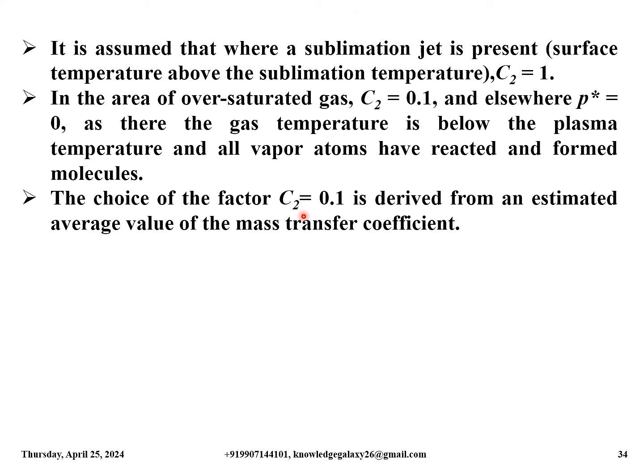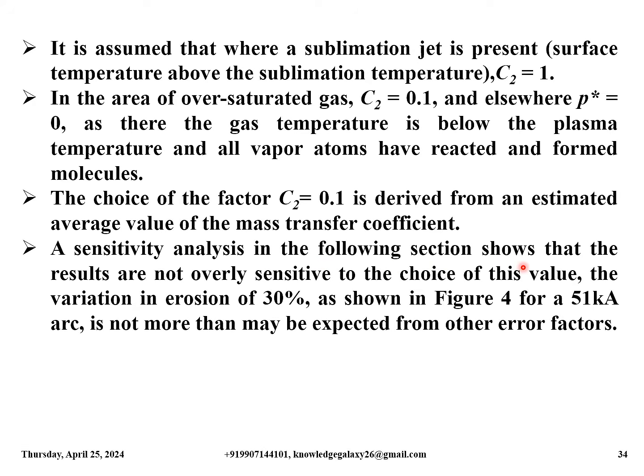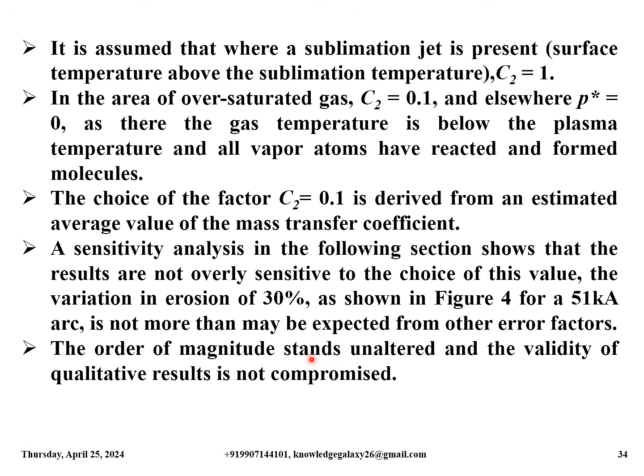The choice of the factor C2 equal to 0.1 is derived from an estimated average value of the mass transfer coefficients. A sensitivity analysis in the following section shows that the results are not overly sensitive to the choice of this value. The variation in erosion is 30%, as shown in figure 4 in the coming slides for a 51 kA arc, which is not more than may be expected from other error factors. The order of magnitude stands unaltered and the validity of qualitative results is not compromised.